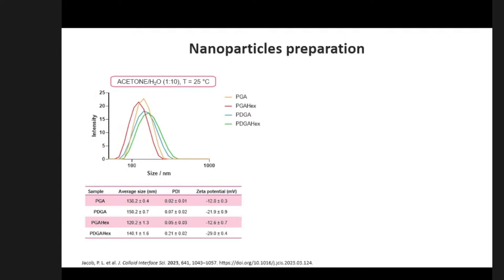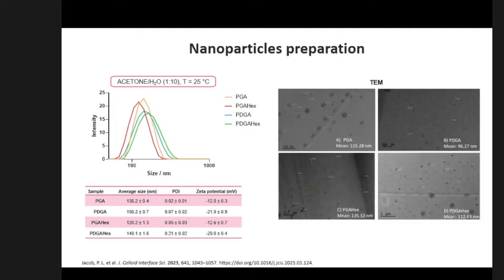Then nanoparticles were prepared by nanoprecipitation method in water, forming narrowly dispersed nanoparticles with sizes between 120 and 150 nanometers, and the zeta potential was negative for the prepared nanosystems, and this was highlighted for PDGA-based polymers because the presence of more hydrophilic hydroxyl groups led to the formation of a more stable hydration shell which interacts better with water. Sizes and shapes were also confirmed by TEM.